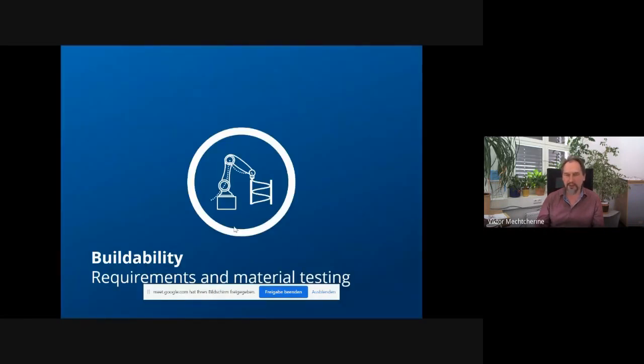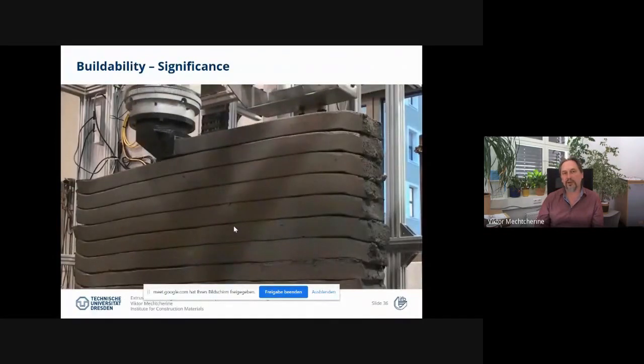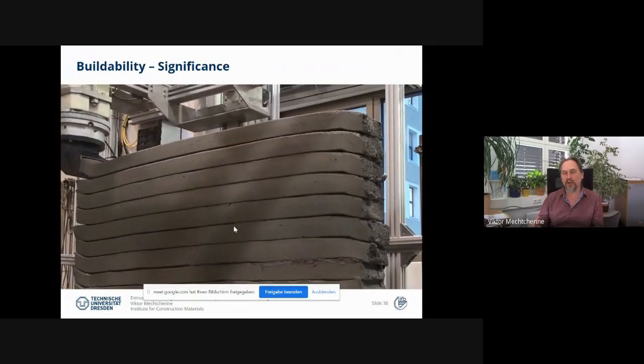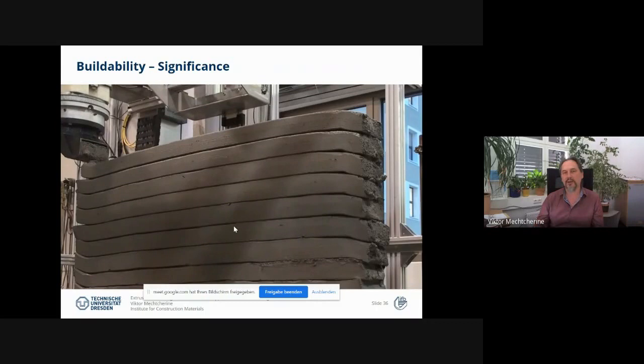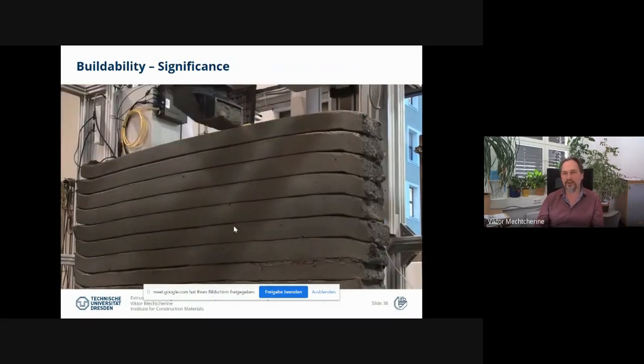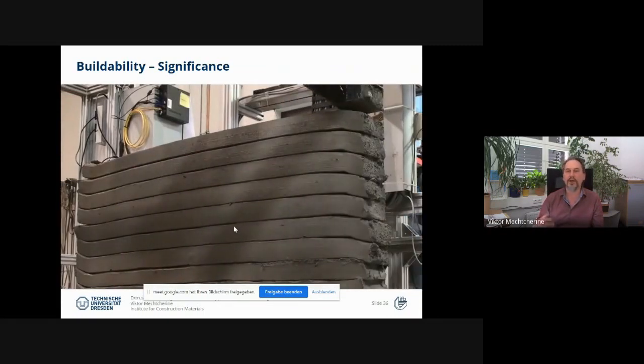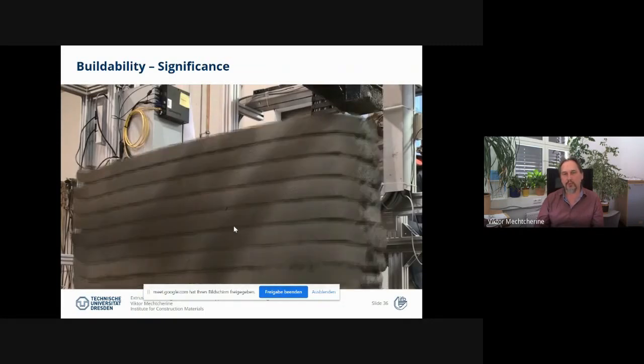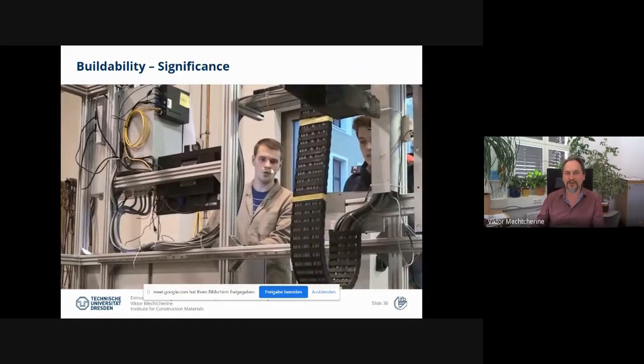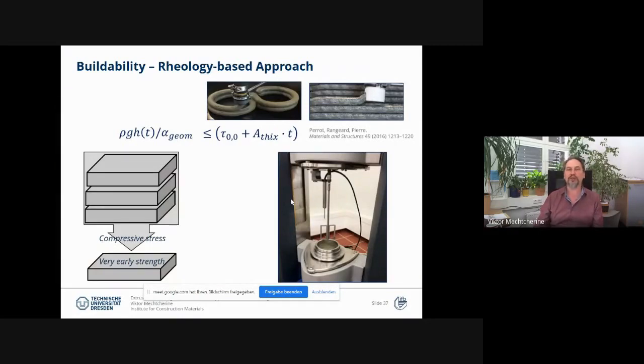So I come to the buildability now, and we proceed here in the first place by printing just simple wall elements and looking at when they fail. So actually the failure is here the goal of the testing. And in this experiment, obviously this goal was achieved, even if my colleague here is a little bit astonished, but if I would continue the video, you would see that he is actually happy that these results were achieved. It's like also in mechanical testing, so you produce specimens with the only goal to destroy them, so to get the results. So in this case, the result is the height of the printed element, which hopefully corresponds with the prediction. So how to come to such a prediction of the height?